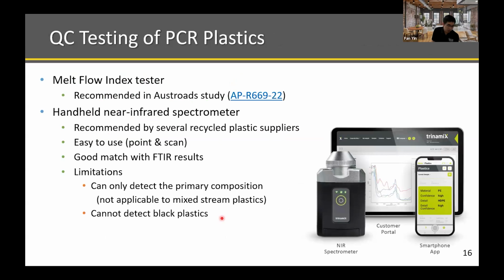The other thing that I want to share really quick is the QC testing of the plastics. One thing that has been identified as a knowledge gap is the QC testing of the plastic. How do we know the material we are using during production is the material that we were told about by the manufacturer? There are really two ways that we recommended from this research. One is the melt flow index. This is a well-established methodology in the plastic industry that gives you the relative flow properties of the material, which can tie indirectly to the type of material in those recycled plastics.